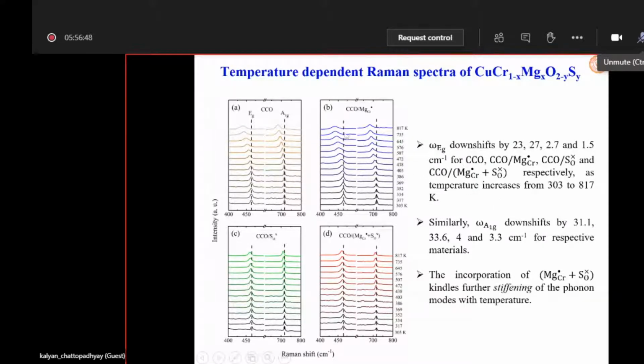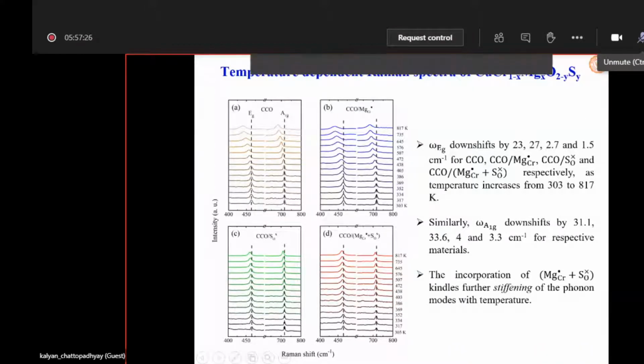Now, this is interesting, and I just want to spend one or two minutes here. See, this is the temperature dependent Raman spectra of all four types of samples. The leftmost upper panel, A, is the pristine copper chromium oxide, and you see that we varied the temperature from 303 to 817 Kelvin, and of course you get the EG and A1G peaks, as I said. But look at the effect of temperature on the Raman spectra. Both the EG and A1G peaks shift to lower wave number, lower Raman shift. So that means thermal softening of the phonon is taking place for both modes, in the case of the pristine sample.